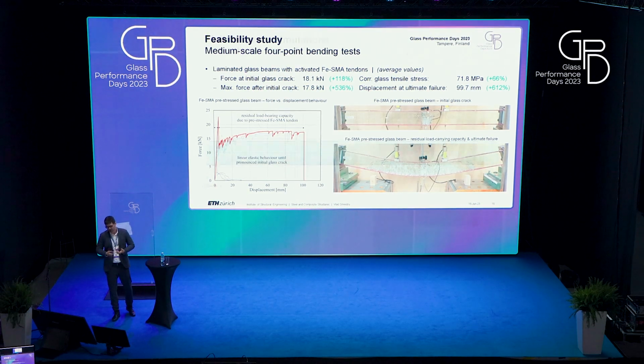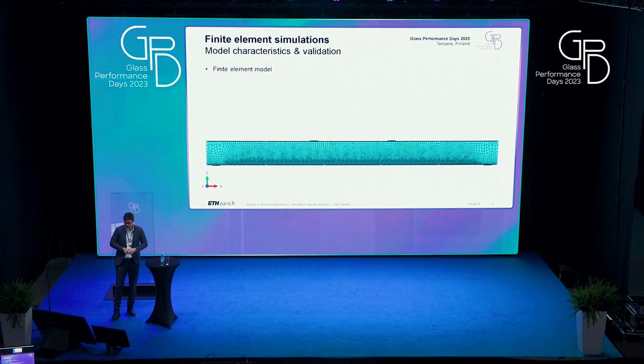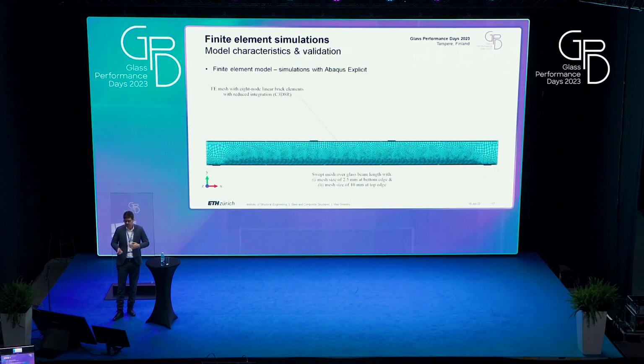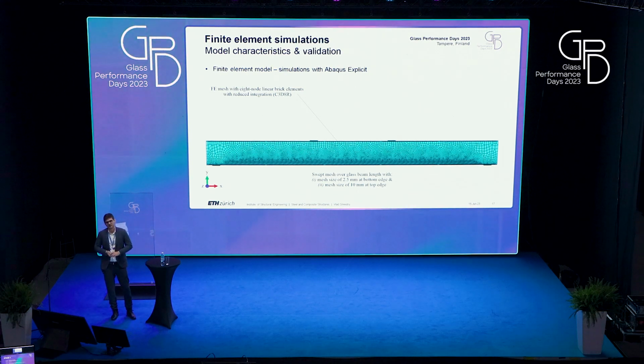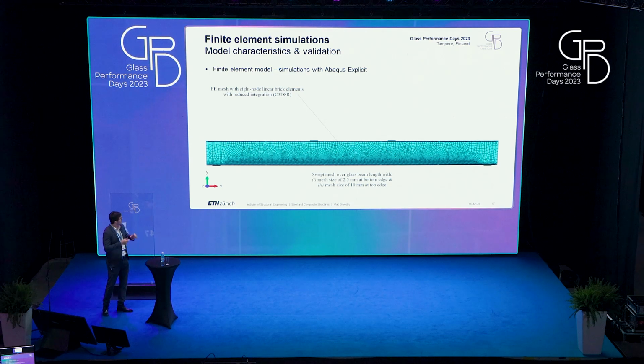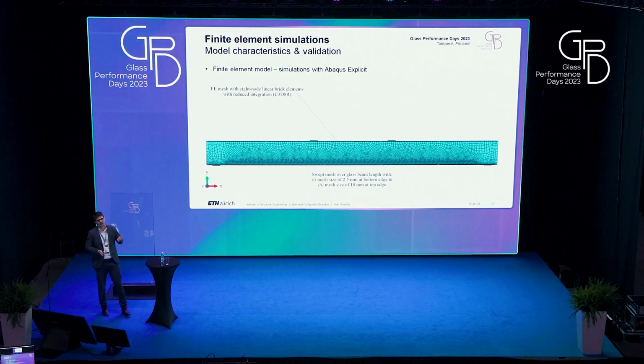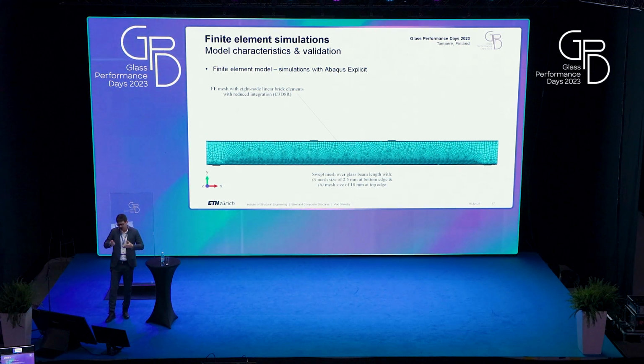And for that, we developed a finite element model in Abaqus based on different literature references that are available. We used Abaqus explicit for it, and the mesh looks very detailed at the bottom because here we expect the cracks, and it's a little bit coarser along the top edge.